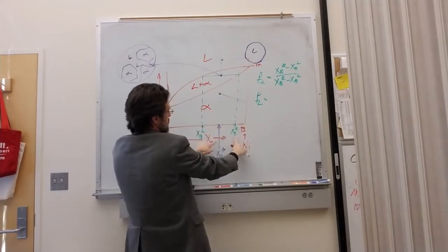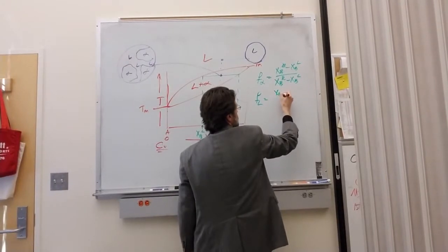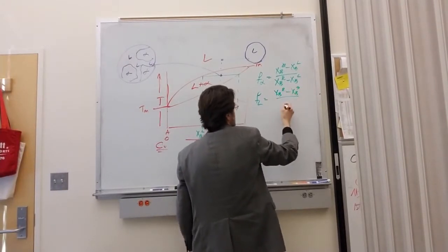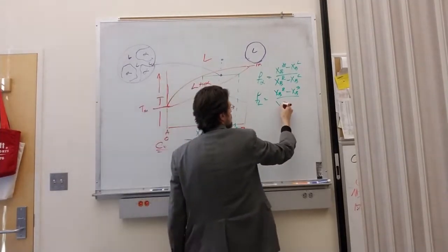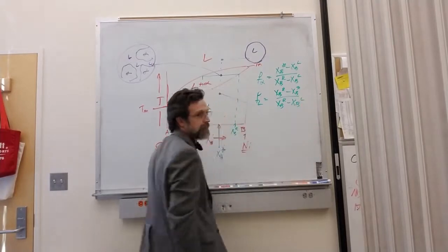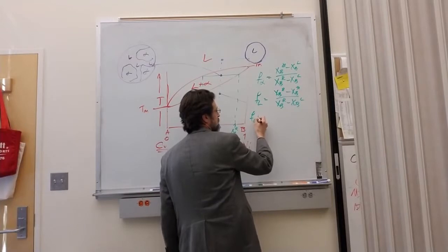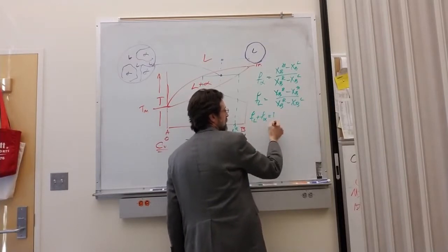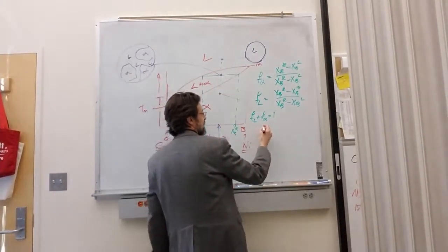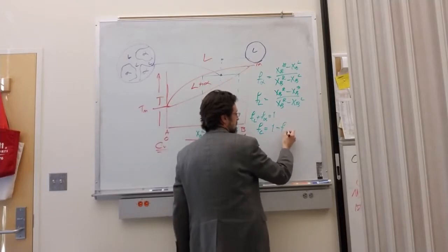So that's going to be XB alpha minus XB star divided by XB alpha minus XBL. It's noteworthy that FL plus F alpha equals 1, because if you get one of these right, then the shortcut is just to say that FL is equal to 1 minus F alpha.